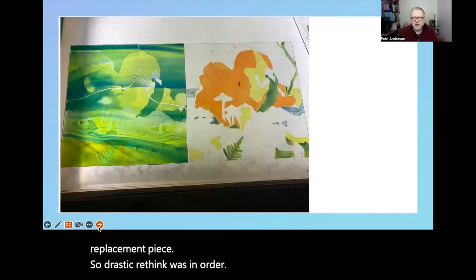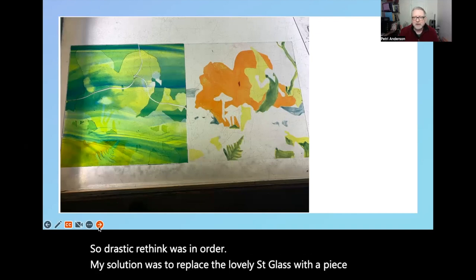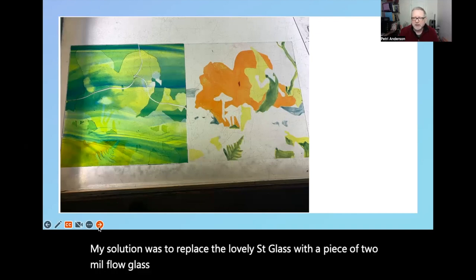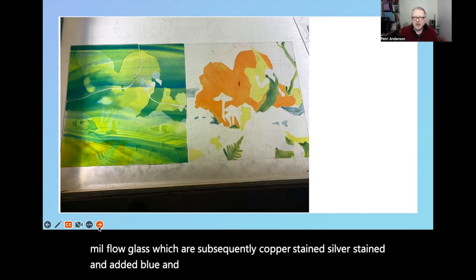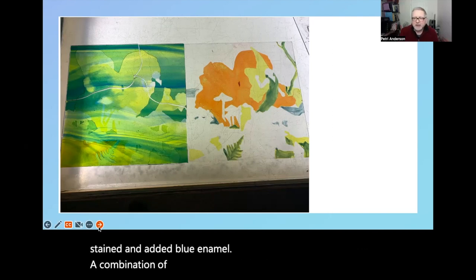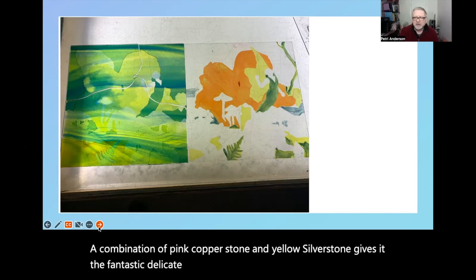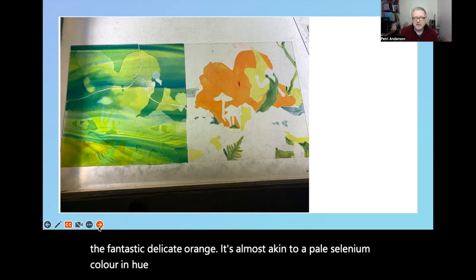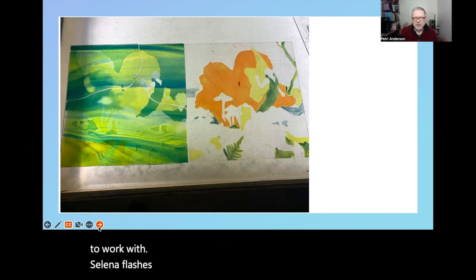My solution was to replace the lovely streaky glass with a piece of 2mm float glass, which I subsequently copper stained, silver stained, and added blue enamel. The combination of pink copper stain and yellow silver stain gives a fantastic delicate orange. It's almost akin to a pale selenium colour in hue, but a fraction of the cost, and much more versatile to work with. Selenium flashes can be a swine to etch, and they're prone to changing colour in the kiln.